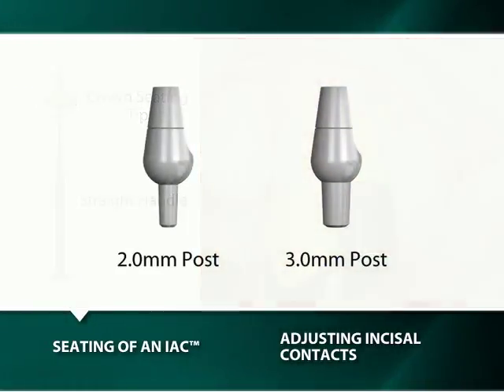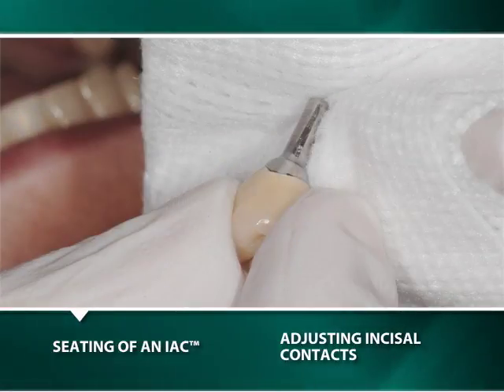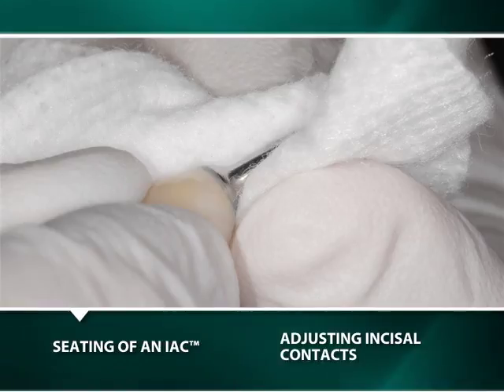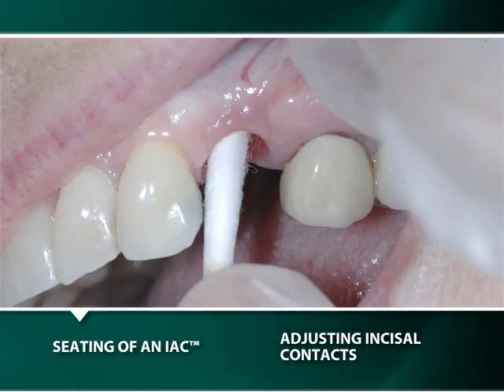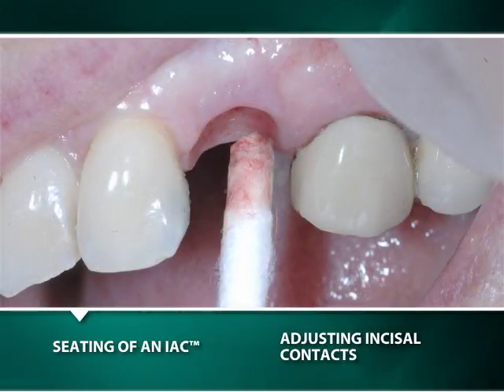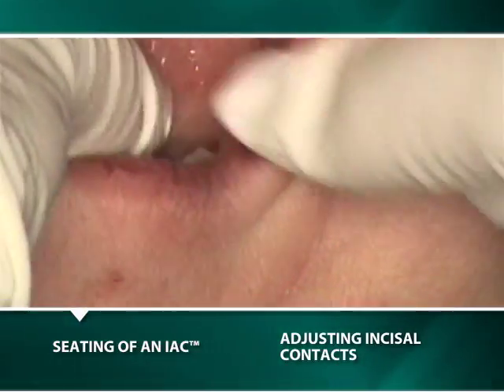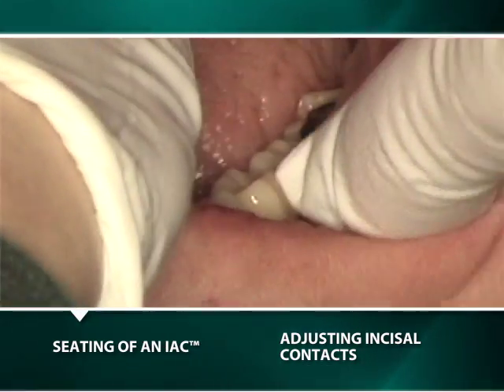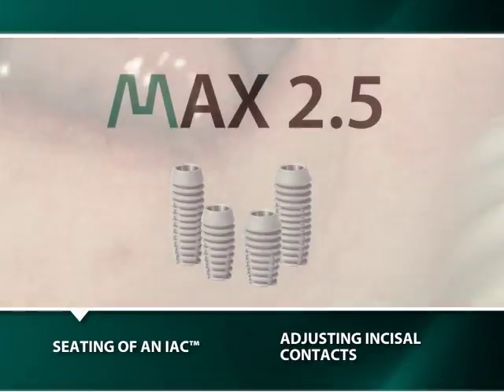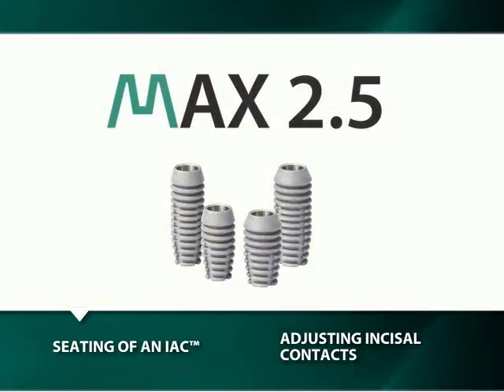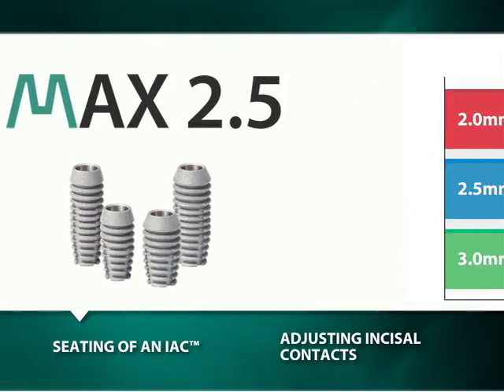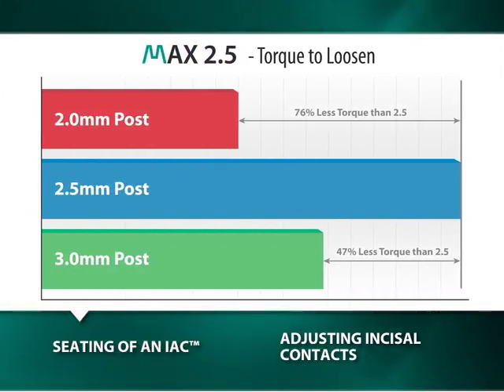If there is a concern for the potential loosening of a maxillary anterior abutment or IAC with either a 2 mm or 3 mm diameter post, then meticulous attention should be paid to the cleaning of both the abutment post and the implant well with alcohol prior to the IAC being inserted. Contaminants such as blood or glove powder can reduce the efficacy of the locking taper by 50%. Confirmation of passive interproximal contacts should be done several times while the IAC is receiving definitive intermittent seating taps. The use of Bicon's Max 2.5 implants provides clinicians with a significantly tighter abutment connection and virtually eliminates the concern for inadvertent abutment loosening.